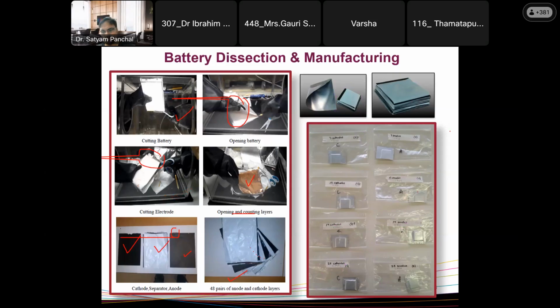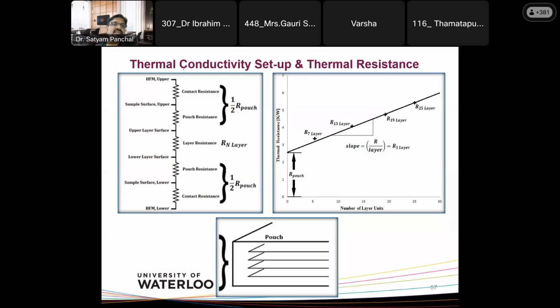Okay, good now. And then the thermal conductivity setup and thermal resistance measurement. So different layers: the top one is the aluminum contact resistance, then the pouch resistance, and then the layer resistance, and then thermal resistance in Kelvin per watt was measured for the number of units. So the 7 layer, then the 13 layer, and then 19 layer and 25 layer were measured, with the slope provided over here.